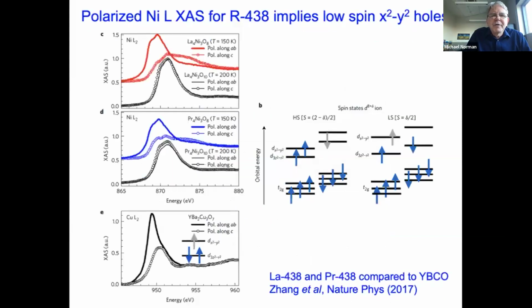So if you look at polarized X-ray absorption data at the nickel L edge, on the top in red is the 438 lanthanum, in the middle is the 438 praseodymium, and the bottom is YBCO. You see two polarization geometries, polarization in plane or along the Z-axis. You can see that YBCO looks very similar to praseodymium lanthanum. And what that means is the unoccupied states are primarily X squared minus Y squared. And so you get this sort of low spin X squared minus Y squared holes, somewhat reminiscent of what you see in cuprates.